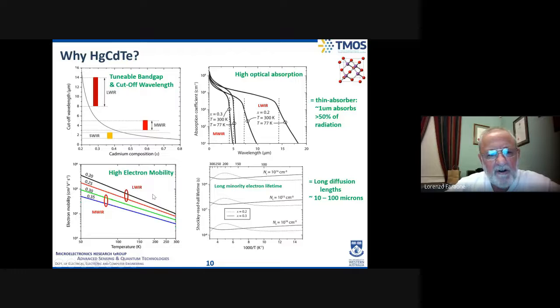And then if you look at the electron mobility, mercury cadmium telluride has a very high carrier mobility. We're talking about, for electrons, around 10 to the 5 centimeters squared per volt second.